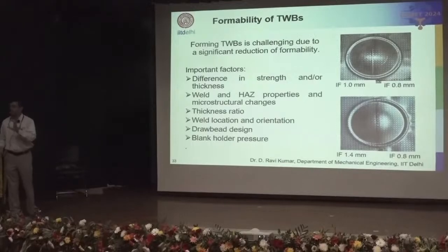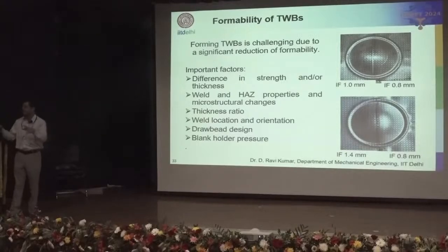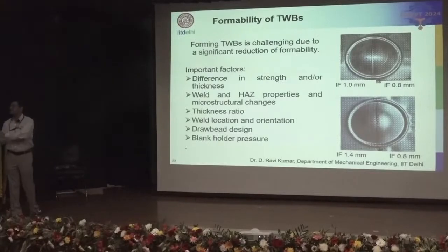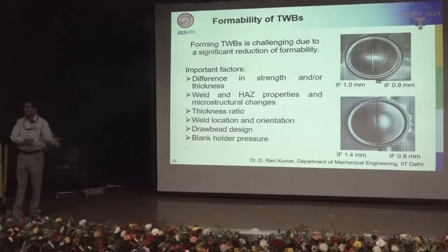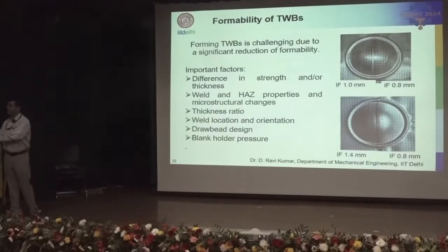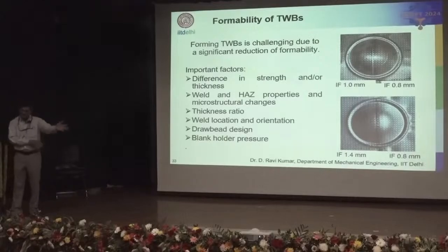But when it comes to forming of tailor welded blanks, there are certain challenges. If you have one single sheet which has the same properties everywhere, it is very easy to predict everything because the material behaves in the same way. But now I have a tailor welded blank, I have a weld line in between. On one side, for example, I have a thicker sheet. On the other side, I have a thinner sheet. Similarly, I have one grade of steel on this side, one grade of steel on the other side.